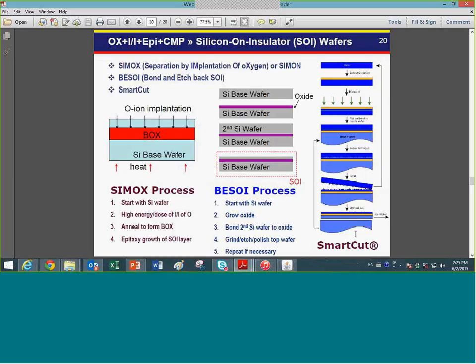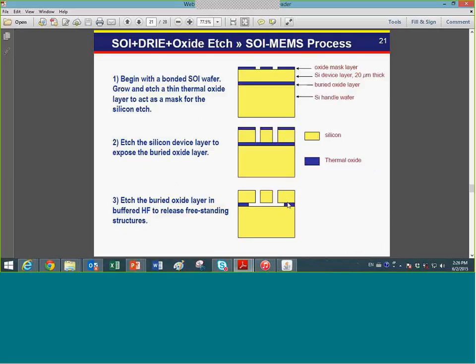This is also a very popular technology. The very conventional one is BSOI. This process involves oxidizing a wafer and bonding the oxidized wafer with a silicon wafer, and then either grinding, etching, or polishing the top layer to a certain thickness according to the requirement. So this BSOI process allows all kinds of SOI materials, especially for MEMS applications.